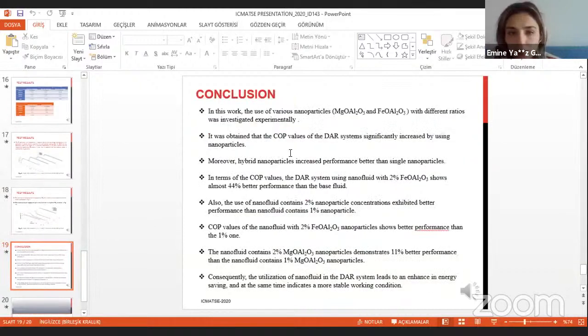So, conclusion. In this work, the use of various nanoparticles with different ratios was investigated experimentally, and it was observed that coefficient of performance values of the DAR system significantly increased by using nanoparticles. And also the nanofluid containing 2% nanoparticle exhibited better performance than the 1% nanoparticle. In the maximum COP values, we get 44% better performance than the base fluid, which is so good in DAR systems, because the COP values are so low.